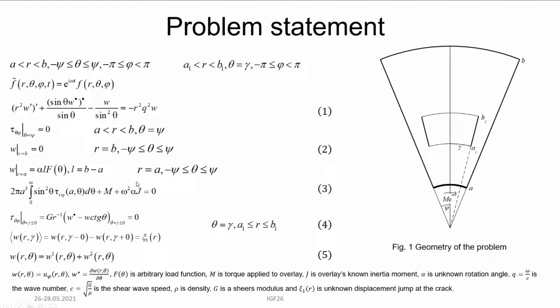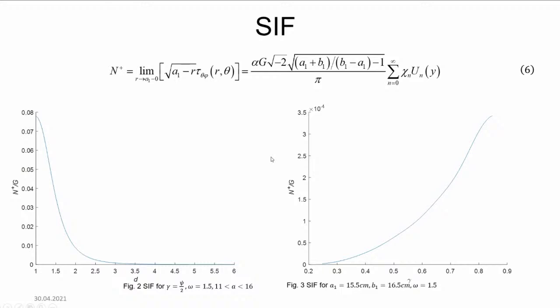Also, the solution was derived with the help of integral transforms and by solving an integral equation with the method of orthogonal polynomials. Here you can see some of the results. For the results, the wave field of the cone was found, and for example, here is the stress intensity factor at the bottom edge of the crack.